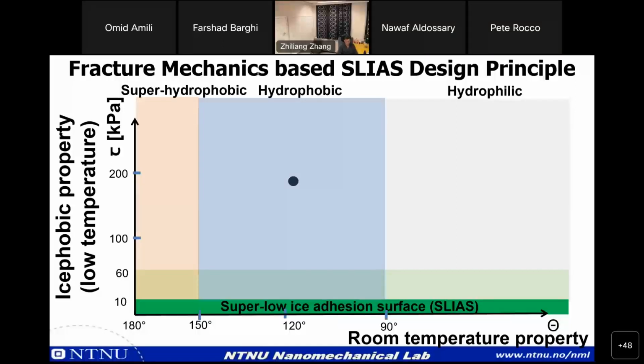So this is a point I want to explain. Above this point, that means when the ice adhesion is larger than 180, we have a very good correlation between the ice adhesion strength and the receding contact angle. This is for smooth surfaces. So for smooth surfaces, this is controlled by the surface chemistry, surface energy. No matter how hard you try, you will not overpass this point.